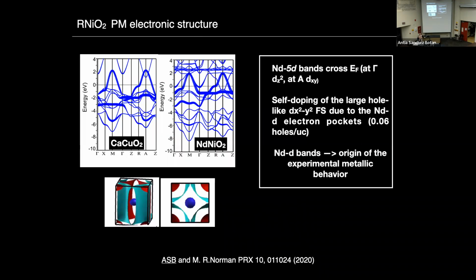So what did we decide to do? Well, we first wanted to look at the basic electronic structure of this material using density functional theory. And we looked at first, of course, at the paramagnetic electronic structure. And what we wanted to do was actually to contrast this nickelate with its cuprate analog, that is calcium copper oxide 2. And these two materials are actually isostructural.